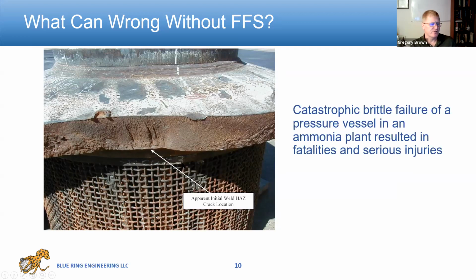What you'll find on fitness for service is most failures actually occur at weld locations. Not all of them. Certain types of damage don't occur at welds, but cracking failures, for example, almost always occur at a weld location. This failure actually, I believe, killed 4 people and caused multiple injuries. So obviously, this is what we want to avoid with fitness for service. We can actually use the material in 579 or other standards, as I'll show you in the course, to determine what size crack is stable and doesn't pose a risk for catastrophic failure.